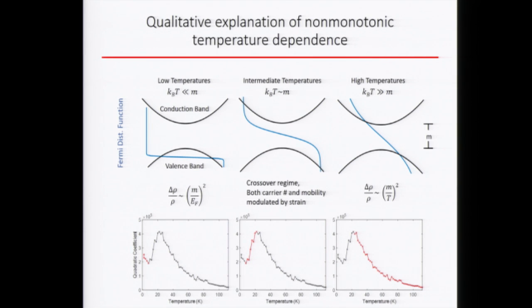At the very beginning, your carrier density is fixed, right? You're in a quantum degenerate regime where the carrier density is controlled by Fermi energy, and when you're changing the mass, you're just changing the property of the quasi-particles near the Fermi energy. Then as you increase temperature, the Fermi energy is a bit blurred, so you have a decrease of this response. But as you go to higher temperature, the thermally excited carriers become comparable to the number of carriers at the Fermi energy. So you have another mechanism to give you a strong strain response, which is that the number of carriers excited across the conduction band and valence band will be strongly modulated by strain.